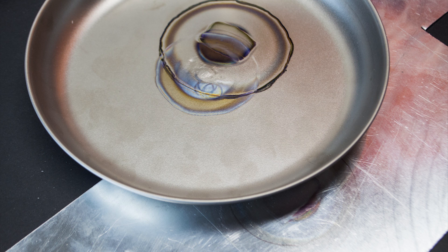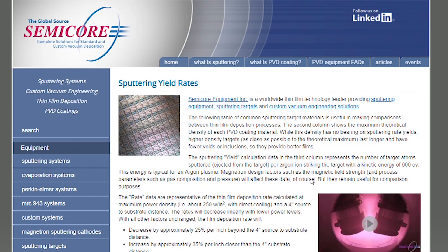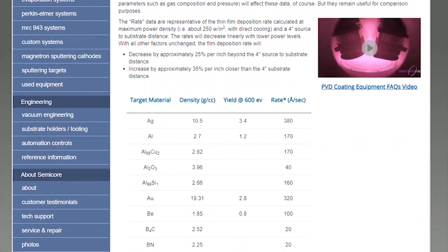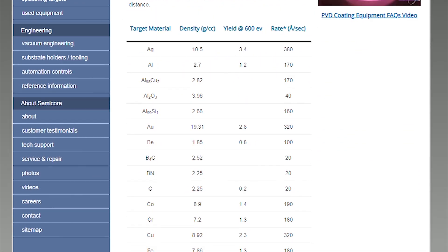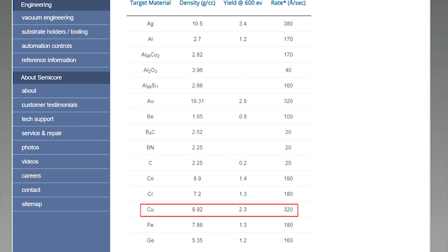It comes down to two things, the first is what's called the sputtering yield rate, and the second is the oxides that form on their surface. The sputtering yield rate is basically a rough approximation of how quickly different materials will sputter over the same process conditions. This site has a great chart which really helps make this clear and I've linked to it in the description. You can see that copper has a pretty high yield rate, which is why even under the relatively high pressure in my chamber, it's still sputtered easily. Now if we look at aluminum, already at a baseline its yield rate is lower.